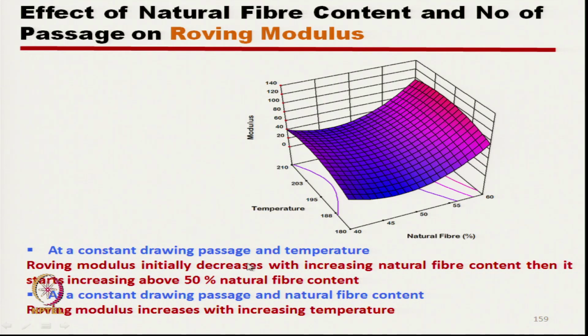So, here at constant drawing passage of 6 and temperature, the roving modulus initially decreases with the increase in natural fiber, and after 50% it increases sharply. And as far as the temperature is concerned, if we increase the temperature, the modulus increases, because again due to proper binding of flax fiber with the matrix. As we increase temperature, more and more melting of the polypropylene fiber takes place, they are binding the flax closely and properly. So, it increases the modulus.